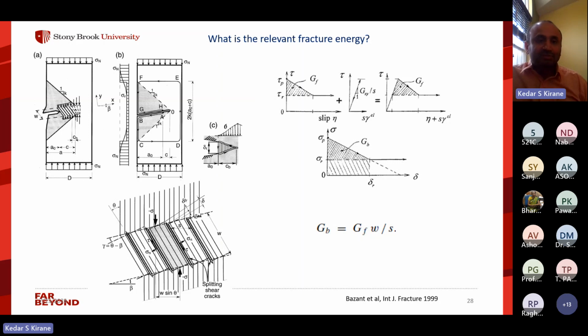So one of the things which is very unclear is what is the fracture energy. We talked about the size effect, but the fracture energy which really governs these kink band failures is not the same as the mode 2 fracture energy. It's a different fracture energy, and we don't know how to characterize it unambiguously yet.